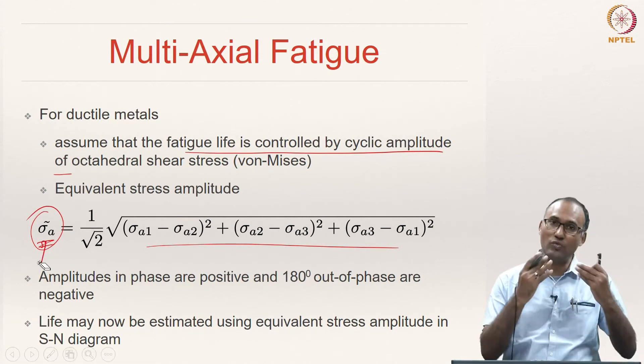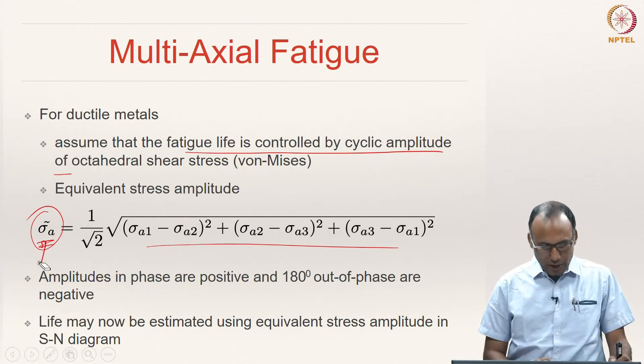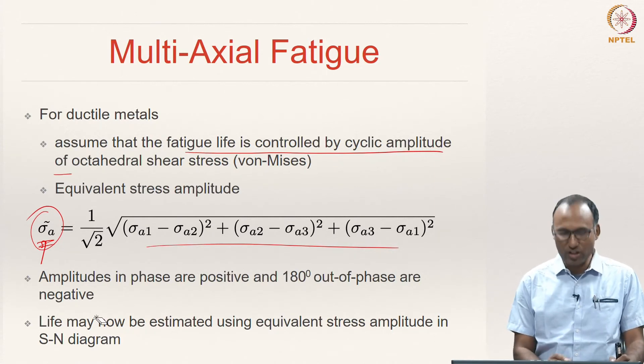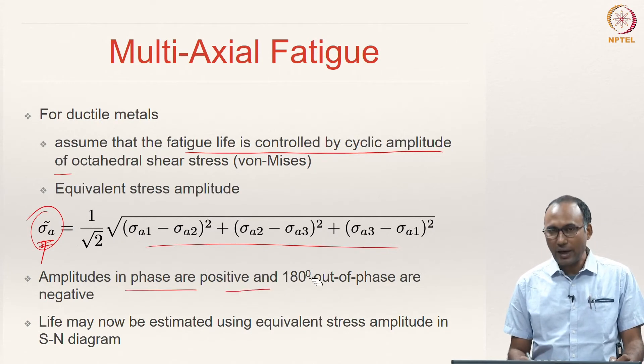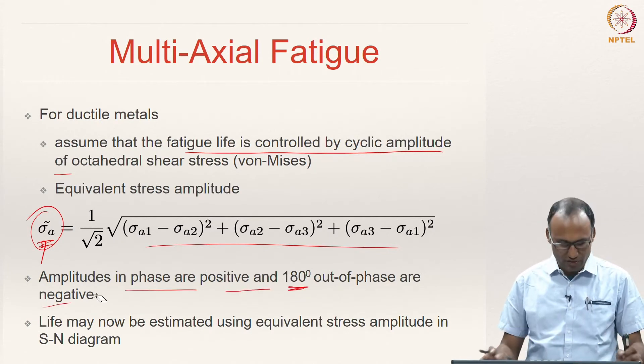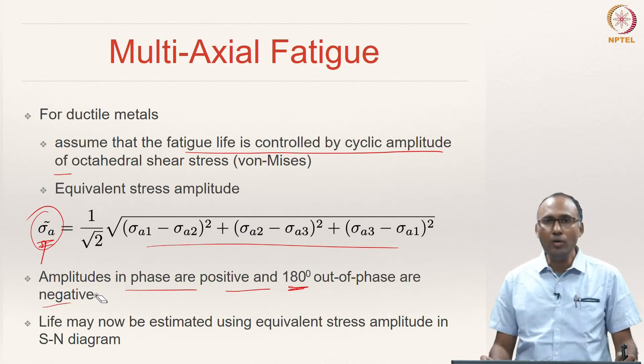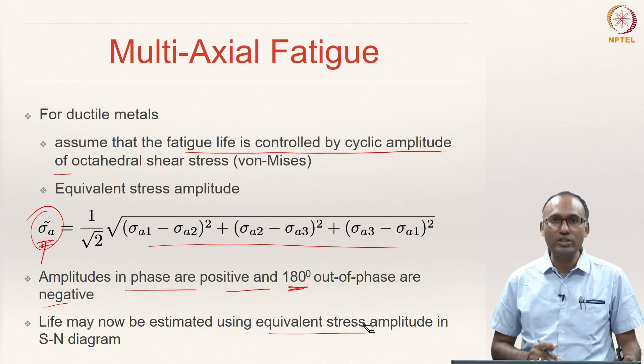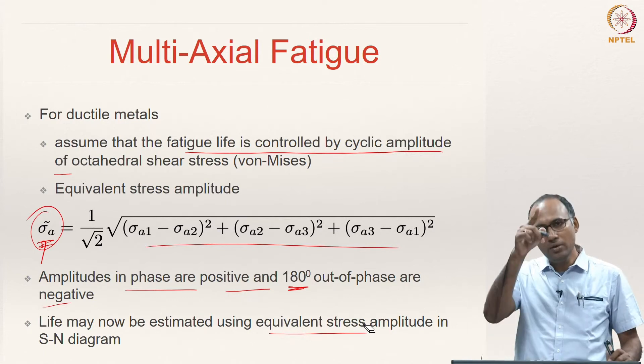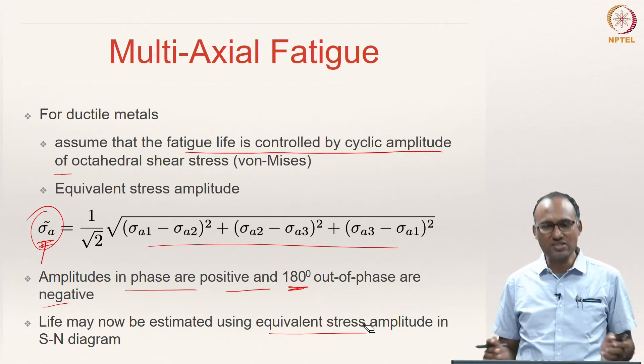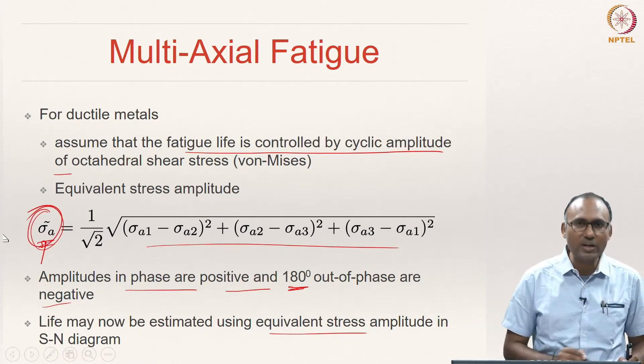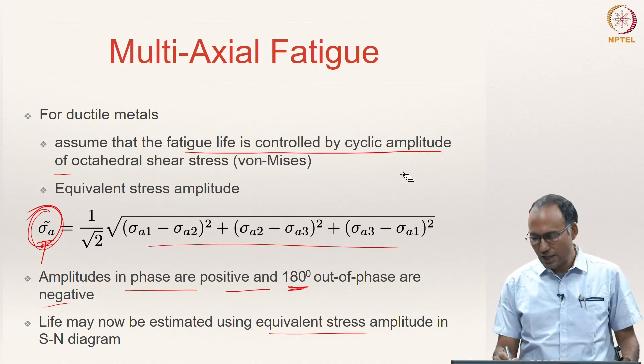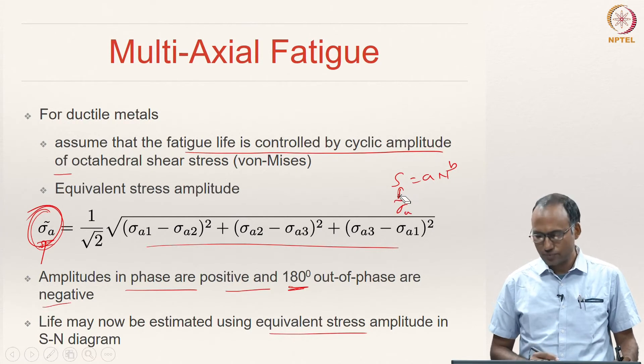While calculating these stress amplitudes, care should be taken: amplitudes that are in phase are positive, and if they are 180 degrees out of phase they are negative. Now you can estimate the life using the equivalent stress amplitude in the S-N diagram. In the S-N diagram, instead of taking sigma a1, sigma a2, sigma a3 separately, you calculate the equivalent stress amplitude and use S = A·N^b where A is your sigma a equivalent.